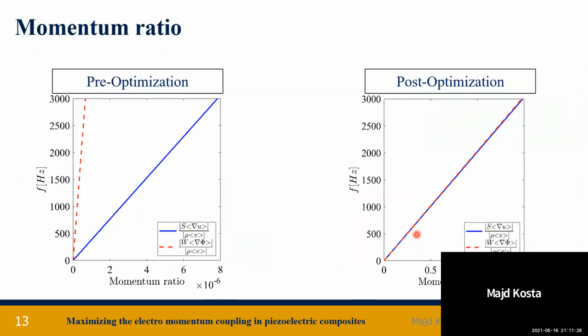So to show the contribution of the optimal design on the balance of momentum, we evaluated the momentum ratio with respect to the mass density momentum, pre and post optimization. And we can see that not only the electromomentum coupling is with the same magnitude now as the Willis coupling compared to the pre-optimization design, but also that both contributions have increased by 3 orders of magnitude, which is amazing in my eyes.